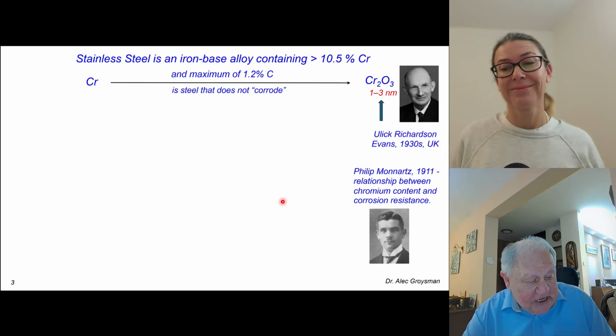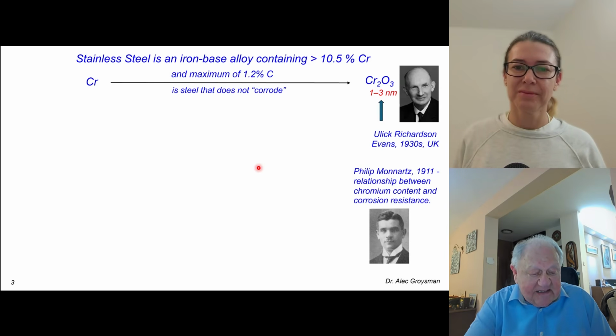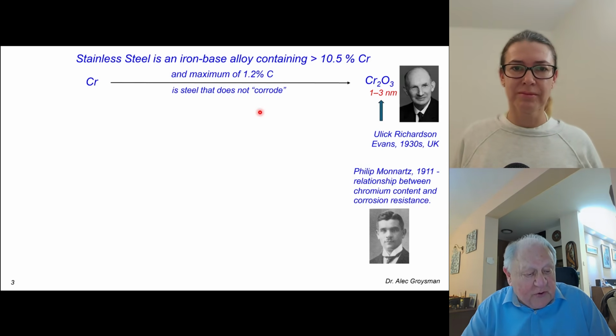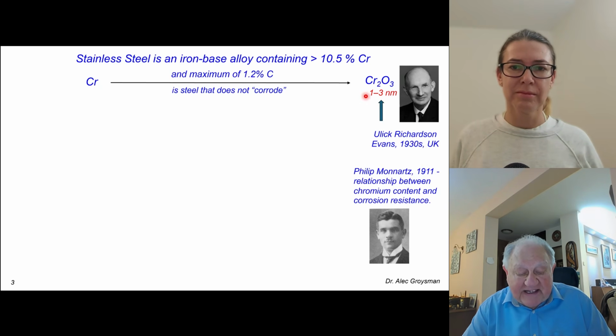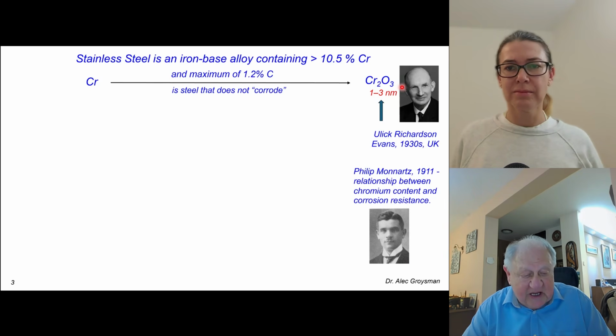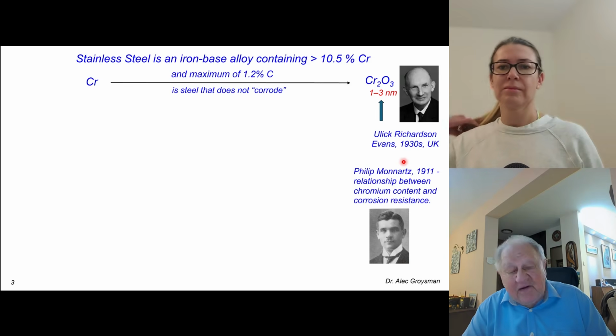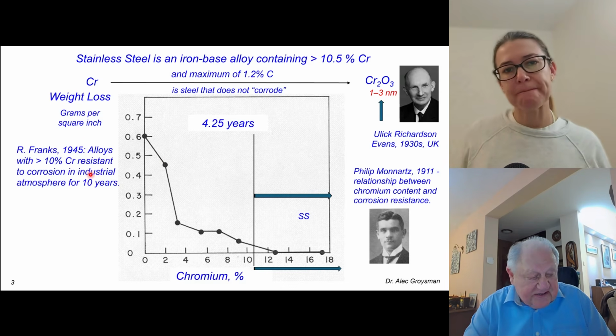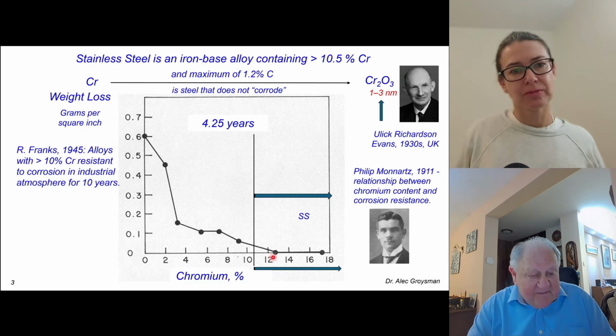And stainless steel is steel that does not corrode. It took about 20 years to prove that a tenacious chromium oxide film was responsible for high corrosion resistance. Ulick Richardson Evans, the father of corrosion science from the United Kingdom, proved this in the 1930s. This graph shows that when we add above 10.5% chromium to iron, the alloy does not corrode in a pure atmosphere.